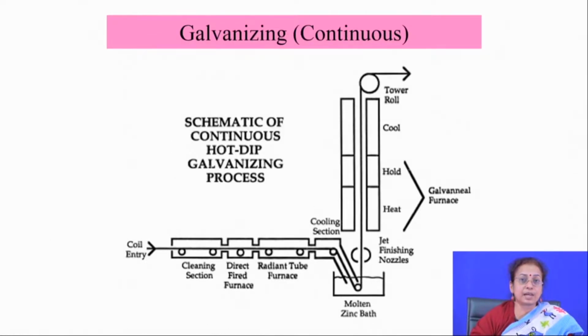Now, one of the biggest advantages of hot dipping is that you get a completely dense coating. You do not really get many defects on the surface of the coating, except the spangle formations and different designs, and microstructural segregation. Apart from those apparent defects, there are not many significant defects observed in the hot dipped coating actually.